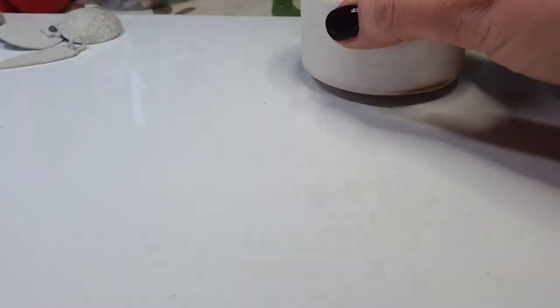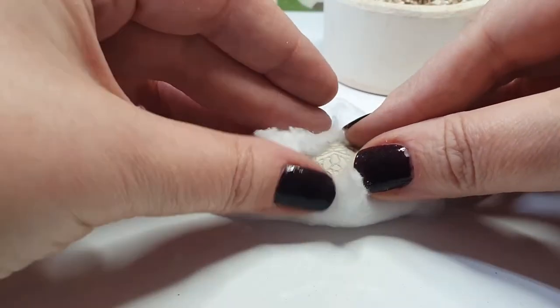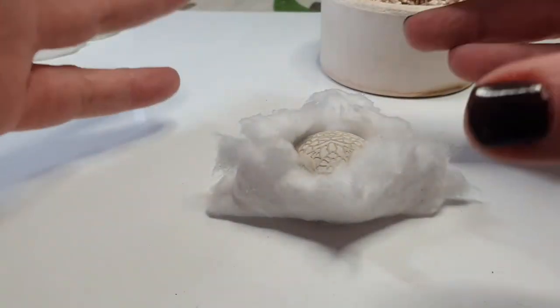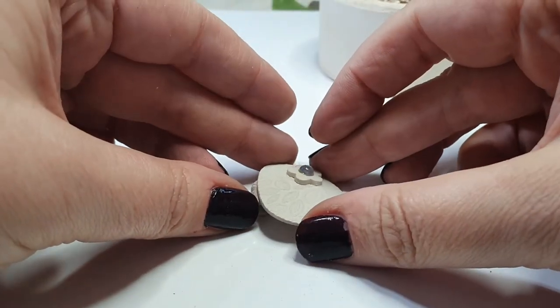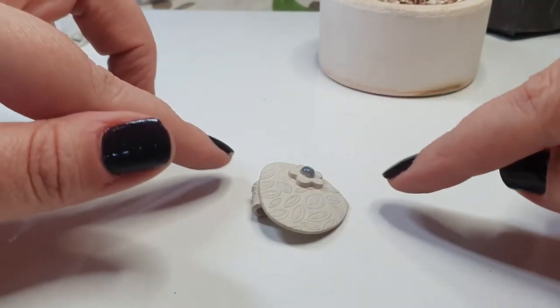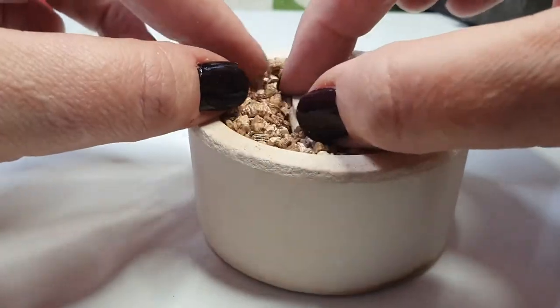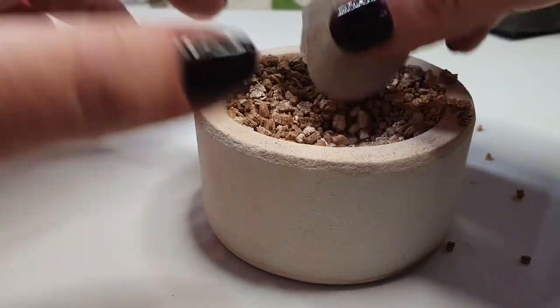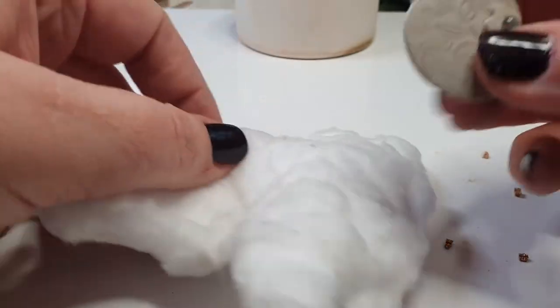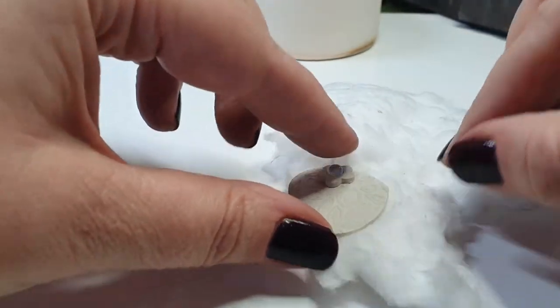As with the flower, you can also open up the kiln pillow and support the bead by cuddling it in, so you've got a nice supportive wall around it so that it stays in place. Now this is a flat pendant with a bale on the back. If I were to fire it flat, this end would curl up — which is not what I want. I need to make sure it's level so it can fire properly. You can fire it in the vermiculite as shown, and as long as you get a nice flat surface it should fire fine. You can also fire it in kiln pillow, but make sure there's a bit of an overlap so the bale is sitting properly.